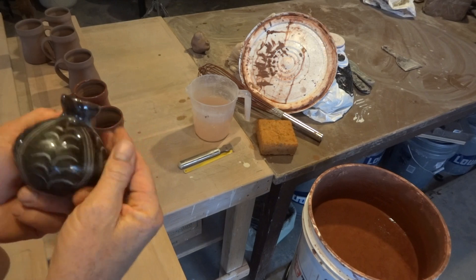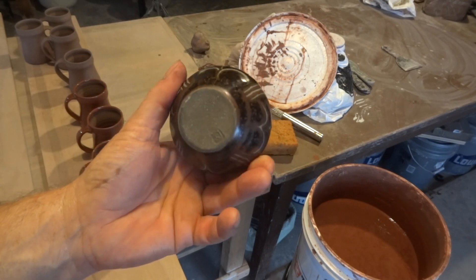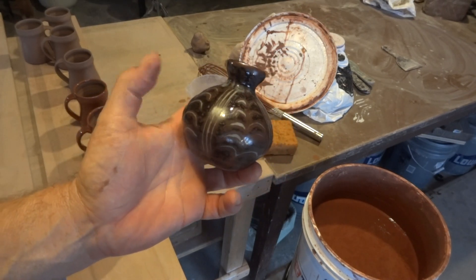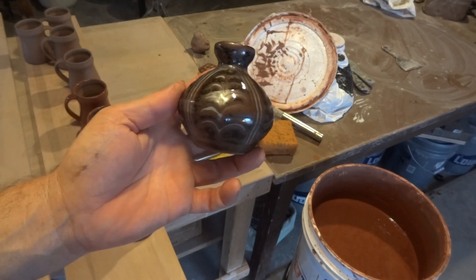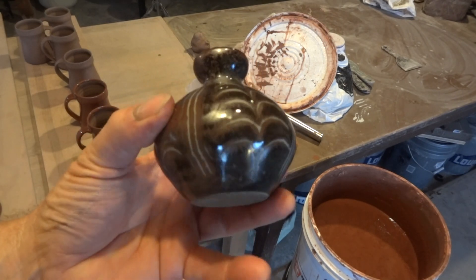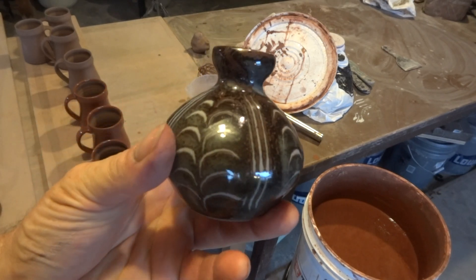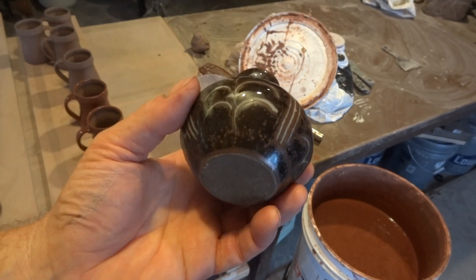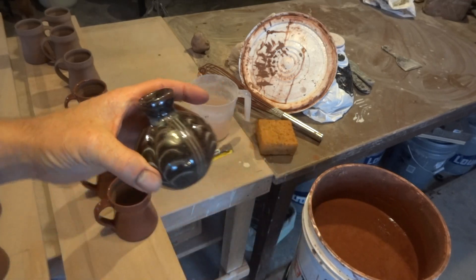Here's a rather good example on this small bud vase of this kind of effect. You've got the red iron oxide slip underneath, the sgraffito decoration showing through, and I've used a combination of a lemon zester and a hacksaw blade to do this decoration. It can vary a lot — sometimes it comes out more gray, sometimes more irony with the iron breaking through the glaze in a spotty fashion.